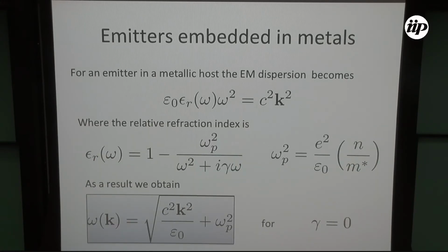So what's the problem of, for example, having emitters inside metals? As we know well from electrodynamics, the electromagnetic dispersion gets modified because now I have a relative dielectric constant here, multiplying the vacuum value. And if we solve this, recalling that the relative refraction index here is 1 minus omega p squared divided by this denominator, where this omega p is the plasmon frequency. If we plug this in the equation above, we get this dispersion relation. So it's no longer a linear, straight line, as in the vacuum case.